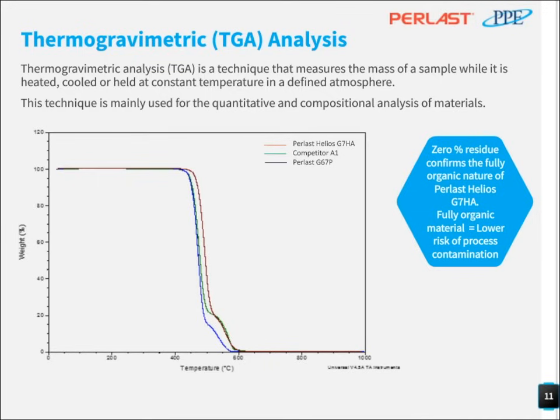So here we tested the same competitor material, and one of our well-known materials, Perlast G67P, and our new material, Perlast Helios. As you can see, the weight loss starts around 420 degrees and then goes down to 0 for all the curves, meaning that all materials tested here are fully organic.